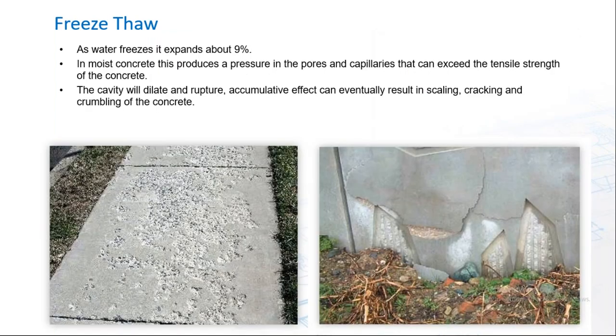Freeze-thaw is also a bit of an issue, where water is allowed to seep into concrete, where it might freeze, and then it expands by about 9% by volume. In moist concrete, this can produce sufficient internal pressure within the pores and capillaries of the concrete to exceed the tensile strength of the concrete. And then we start seeing those cavities dilate and rupture. And ultimately we see scaling and cracking and/or crumbling of concrete. A couple of good examples there with a sidewalk or a brown coat over a scratch where water has been allowed to freeze.